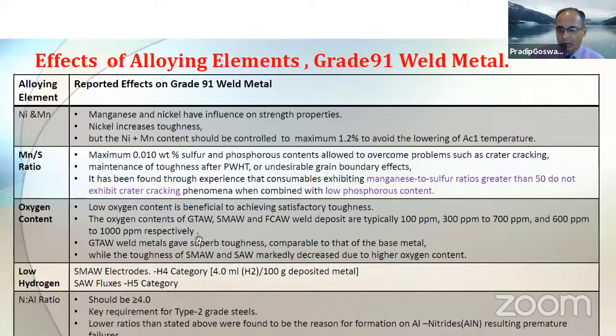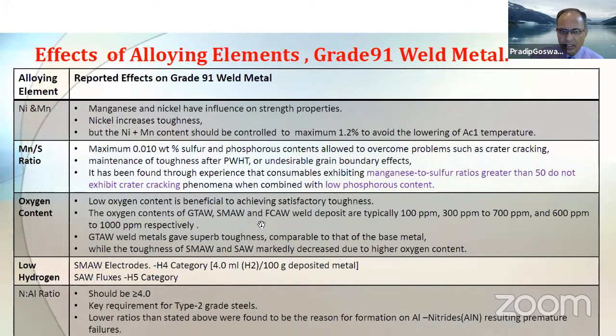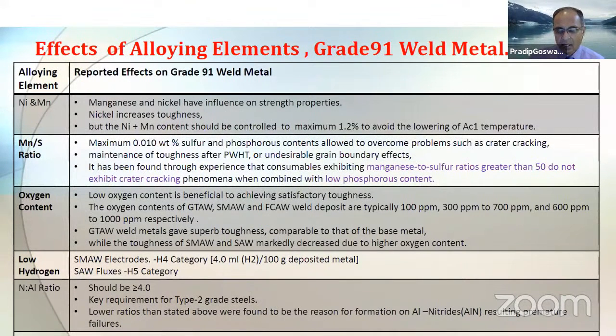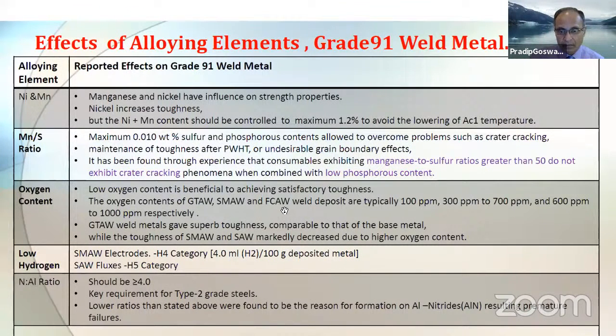Flux core arc welding generally is a common process, but when it comes to the notch toughness, frequently we see that flux core arc welding does not perform as well as TIG, shielded stick or submerged arc welding consumables. One reason for that is that flux core arc welding consumables or weld deposits typically have a higher level of oxygen. GTAW or gas tungsten arc welding metal gives a superb toughness compared to all other weld metals, and those are some of the rules for choosing the welding consumables for this alloy.